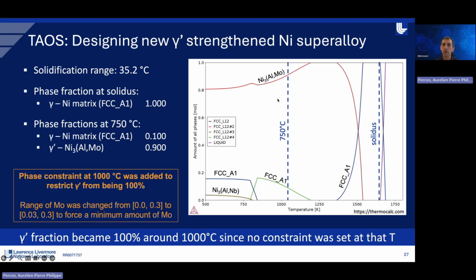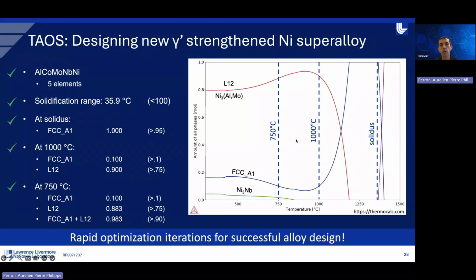You just have to add the same constraint that we had at 750 at 1000 C. And another thing that we did, we also added a minimum composition for molybdenum because we really like to have molybdenum in this L12 phase. So you can tweak your problem, re-optimize, and it worked immediately. So now that we have properly constrained our problem for our application, we see that the FCC phase, initial matrix phase, doesn't go to 0, and that you maintain the amount of ordered phase that you were targeting. So that's really to show you how you can quickly iterate on your optimization problem.